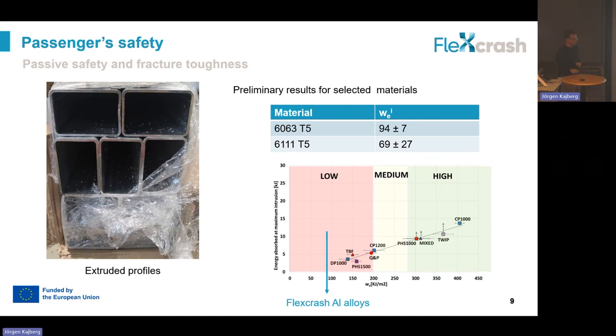So then if we perform this analysis with our materials, the materials selected in the FlexCrash project, here we have the 6063 and the 6111 in T5 condition. In this case, we just performed the tests in some extruded parts, and we identified the required energy to initiate the crack in a material. Well, we can see that we can detect the difference between these two materials, and as we saw in the previous slide, it makes sense to use the material that requires a higher energy to initiate and propagate the crack. So then we will go for the 6063.